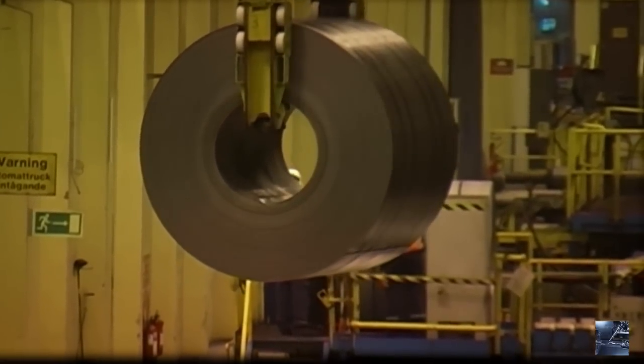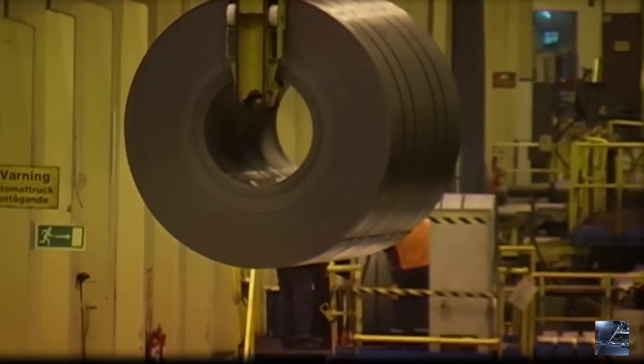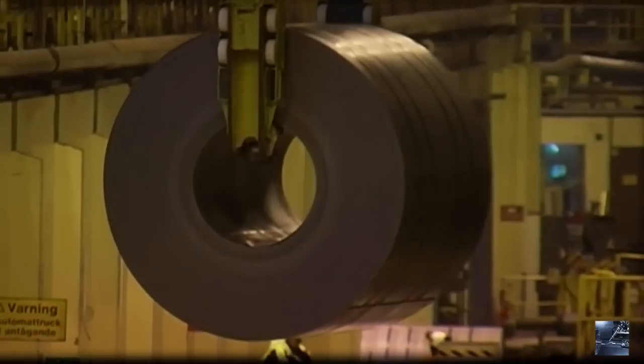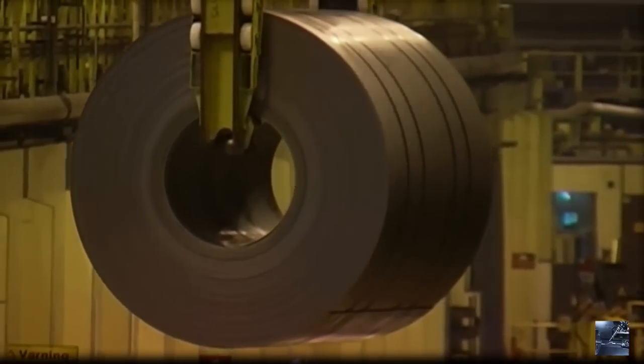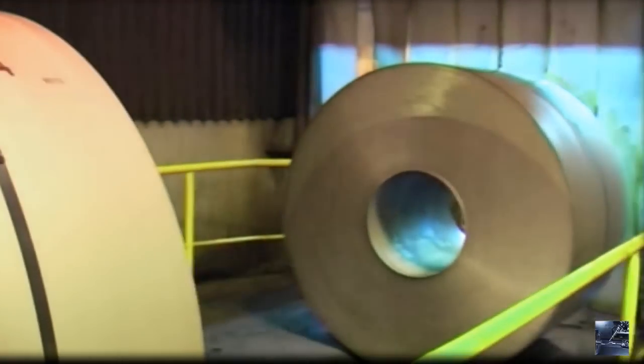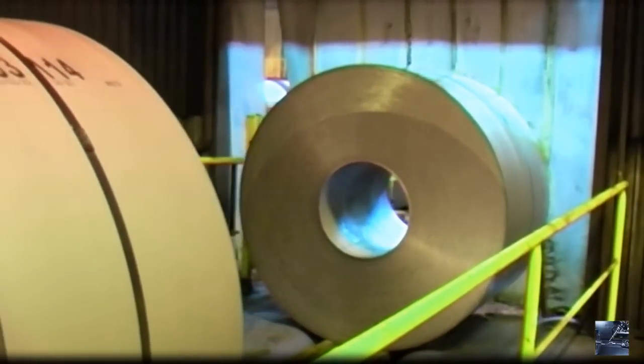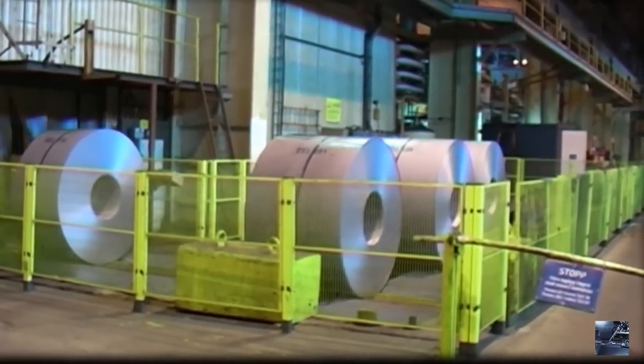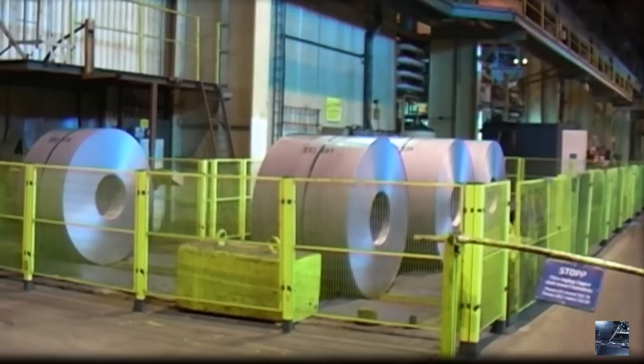The cooling rate is adapted to each strip to produce the appropriate microstructure and material properties of the end product. When the strip is passed through the cooling section, it's coiled in. The temperature during coiling varies between 150 and 750 degrees centigrade, depending on the properties assigned to the material. After coiling and the subsequent cooling, the strip can be sold directly to the customer or undergo additional processing stages, for instance, cold rolling.